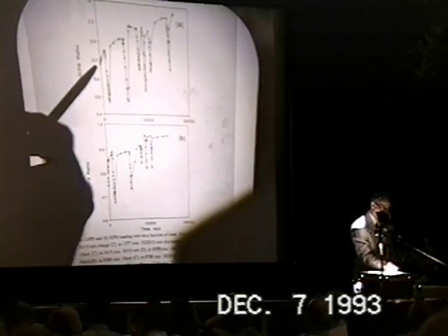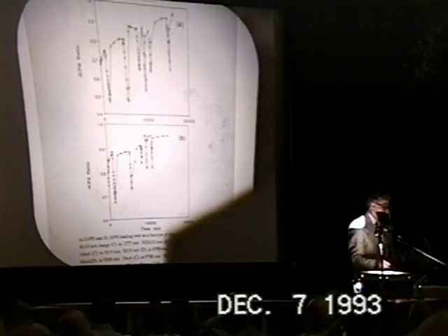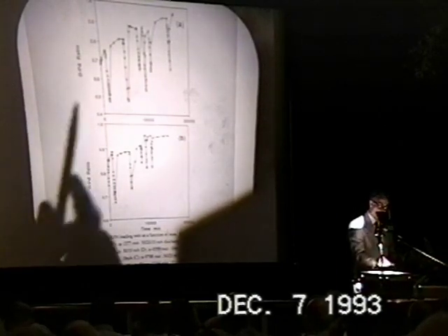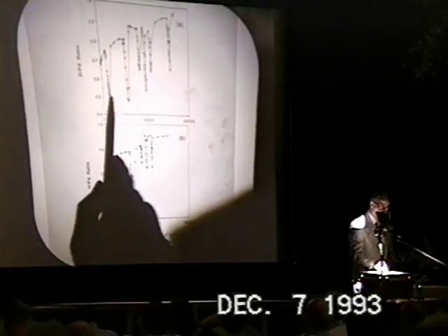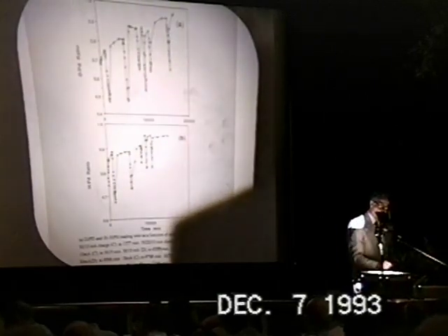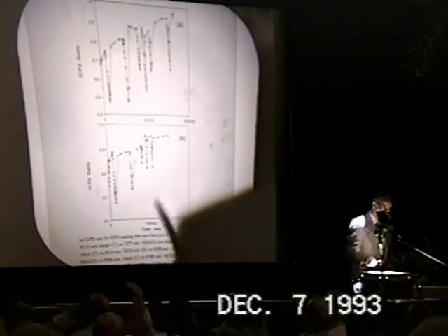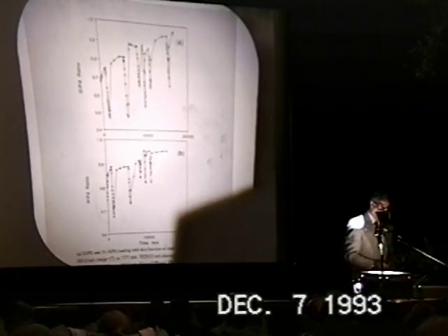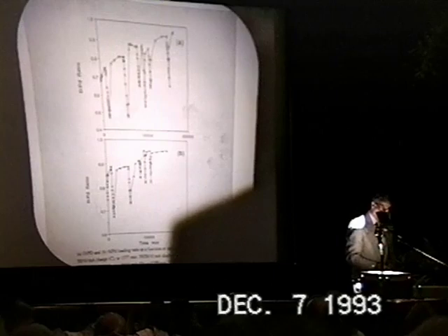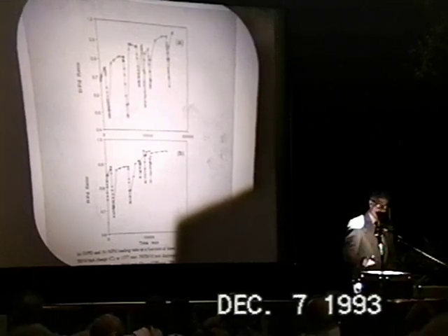we start already with a loading ratio of 0.67 or 0.68, and that's pre-loading. With every loading and unloading and subsequent loading, one typically gets a little bit higher loading ratio, until in most cases shown, we get to loading ratios just under 1, maybe about 0.95, 0.96 or so.